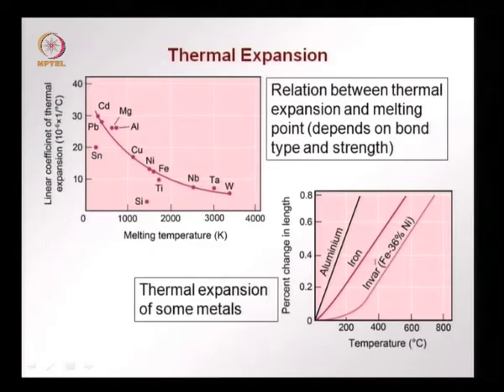On the right we have compared 3 metals as a function of temperature. On the x axis we have a range of temperatures going from 0 to about 800 degrees Celsius, and on the y axis we have a percentage change in length. For aluminum and iron we have a linear increase. The coefficient of this is alpha L, that is the coefficient of thermal expansion, the linear coefficient of thermal expansion. We find that aluminum for the same temperature change expands more than iron, and what is interesting is this alloy